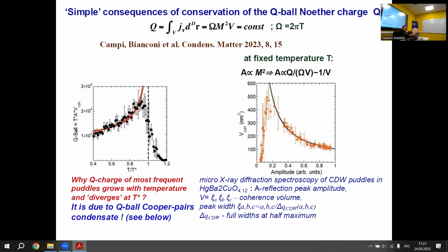So this was noticed by experimentalists because they have measured so-called puddles of charge density waves, localized puddles of charge density waves in cuprates with X-ray diffraction. And this was done in the mercury high TC compound, mercury barium copper oxide, and they found these funny results.